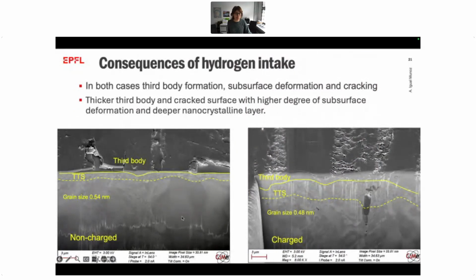On the subsurface, the differences are even more clear. In both cases, the mechanisms are more or less the same. We have the third body here in the non-charged. We have the third body in the charged. We have also the subsurface deformation, the tribological transformed part of the subsurface. Here it is a little bit thicker. But in the charged sample, we have a thicker third body. We have a cracked surface, and then we have a higher degree of recrystallization. The grain sizes are slightly smaller. So there are differences.